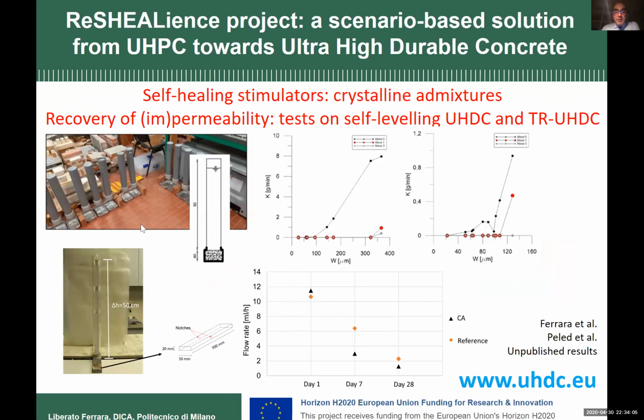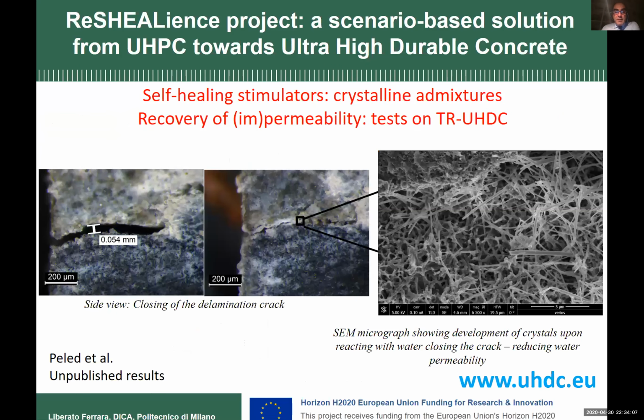These are some results not yet published, obtained by my colleague Professor Alba Peled at Ben Gurion University. The crack closes after just a few months, and you can see the crystalline growth inside the crack, which reconstitutes the true continuity of the material.